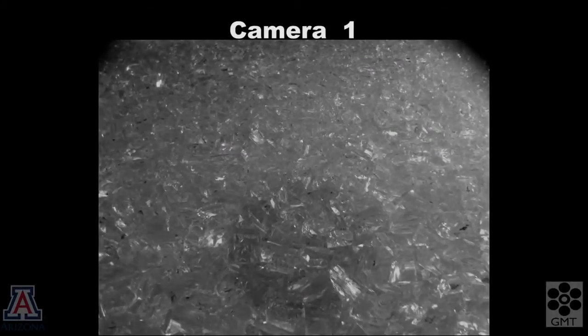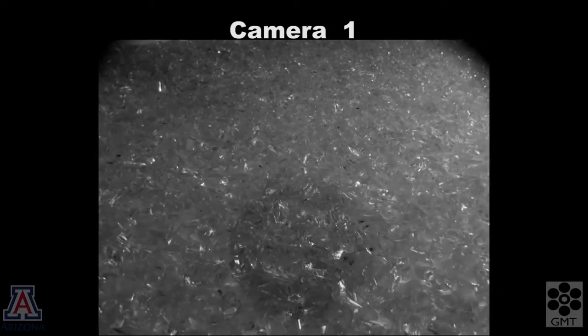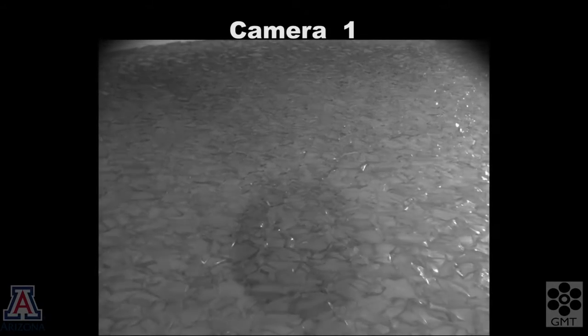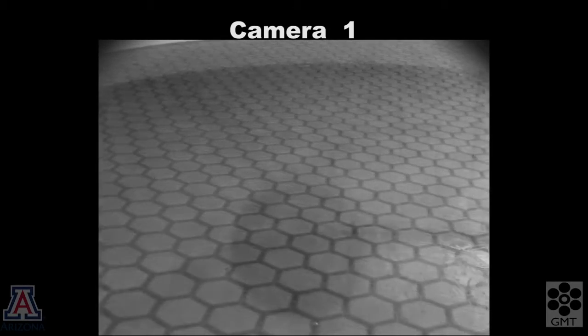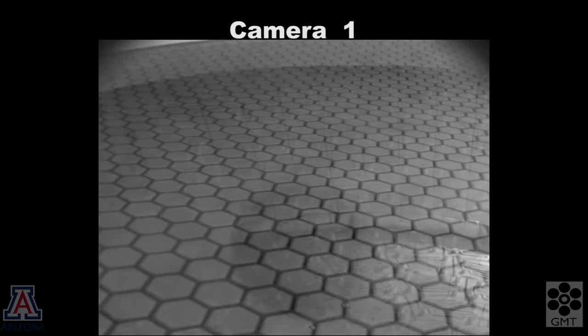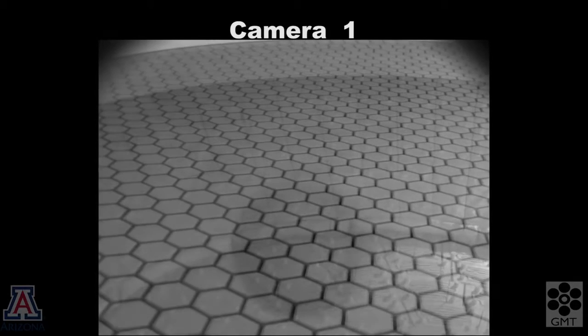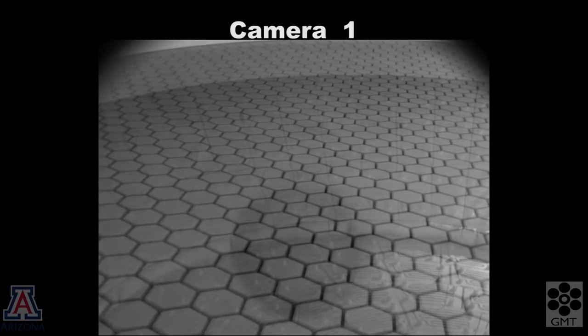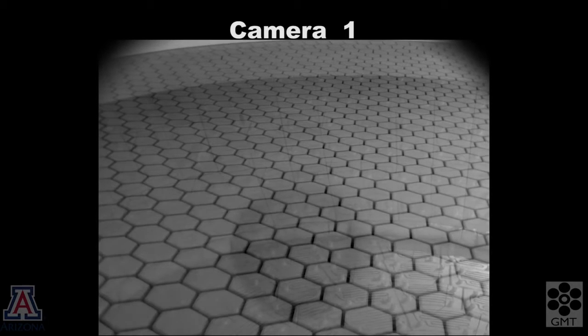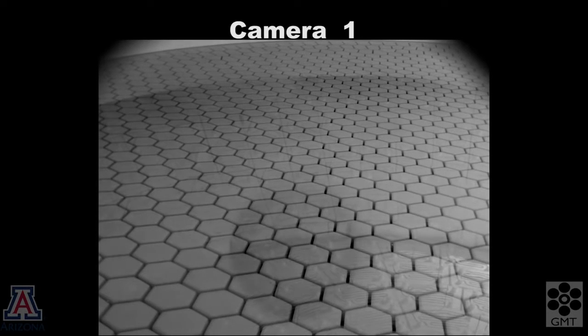Now we'll change to a view from one of the cameras mounted in the ceiling of the furnace so we can watch the glass melt. It reaches a thickness like cold honey and takes a few hours to flow down the 12 millimeter gaps between the hexagonal boxes. As the glass melts, it becomes transparent and you can see the hexagonal boxes. You can also see some bubbles of trapped air rising to the top and bursting.